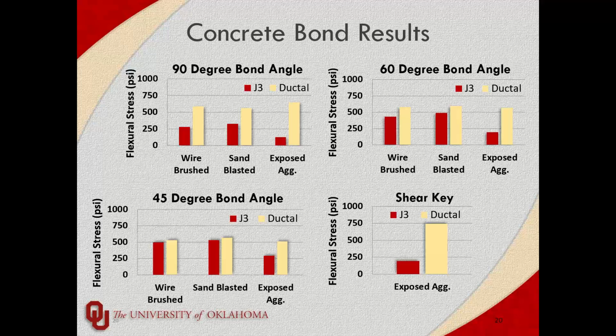We believe it's potentially a twofold reason. One, while Ductal is a proprietary blend, we're fairly certain it does have more silica fume, because most UHPC mixes that you'll see will have anywhere from 15 to 25 or 30% of the cement or the cementitious be silica fume, which is really mainly to increase the density and the durability and the strength.